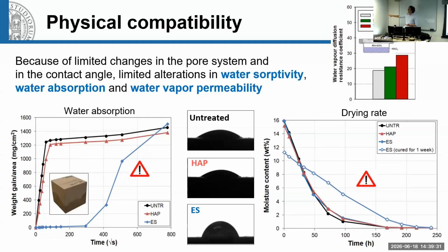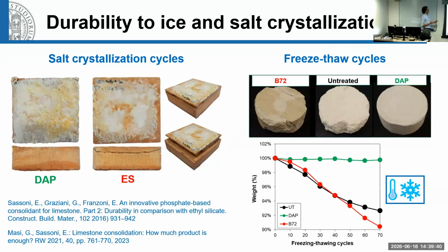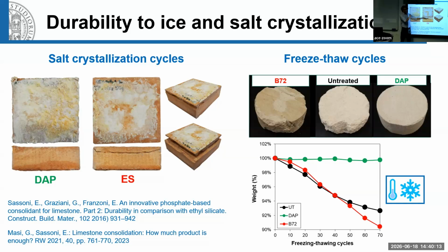One may think, oh, this is good. I have a hydrophobic surface. If it rains, rain is not able to penetrate. This is true, but coming to durability, what happens if, for instance, this is a sample that we treated in the lab? You apply the consolidant, this ethyl silicate, on the surface here, which becomes hydrophobic. The problem is if you have a source of water from behind, for instance, because of rising damp from the ground, which is a quite common phenomenon, at least in Europe, but I guess also here. So here you see what happened to this specific type of sample where the surface was treated, so it became hydrophobic. We sealed the lateral surface and then we let water penetrate from above. After a few cycles, there was a sudden detachment of the consolidated part, which of course is something that you don't want in your model.